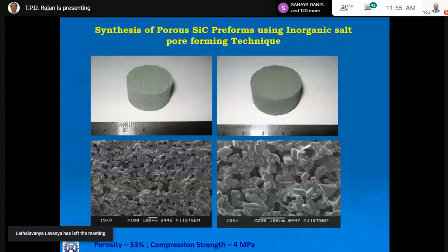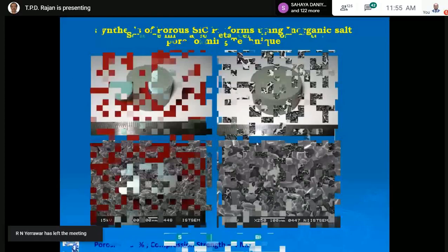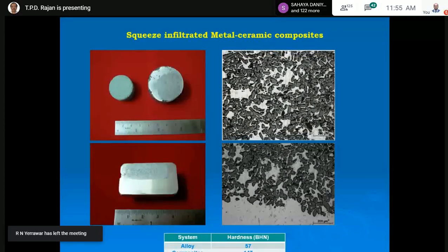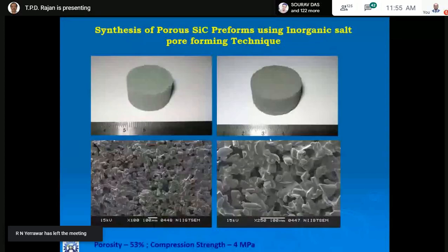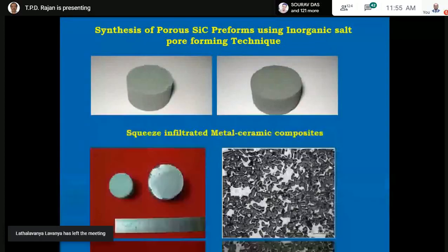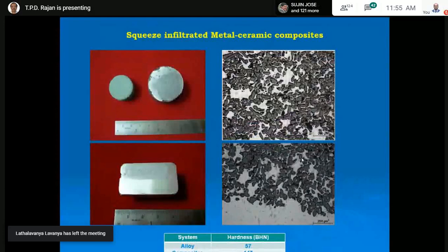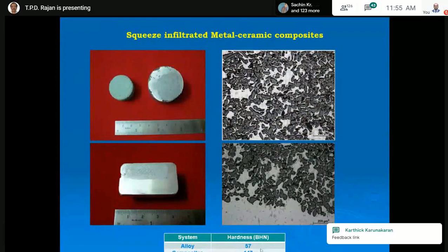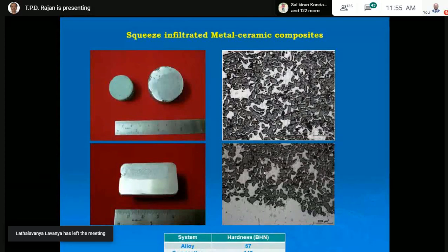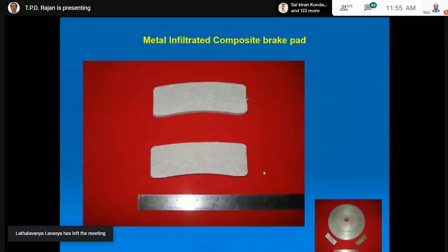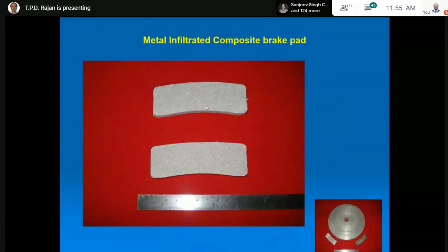So this is a hollow body, and we can infiltrate it with the metal. You can see that this is a porous body, and into these pores the metal is getting infiltrated, and this is an aluminum matrix SiC composite made with the infiltration technique. The advantage is that the alloy has 57 BHN, and the composite has 147 BHN. So metal infiltrated composite brake pads are used because of the friction.